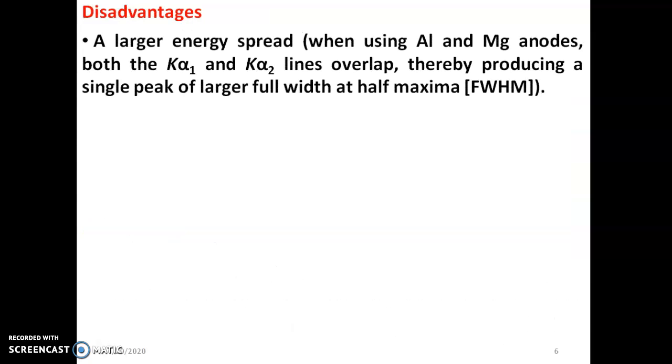But the disadvantage is that in the case of standard sources we can't control the energy spread, because in some cases, even though we use a single source, it consists of different lines which have very closely separated wavelengths. So most of the time they merge together and we get a broad energy spectrum, or the FWHM of the spectrum is very large, very wide.